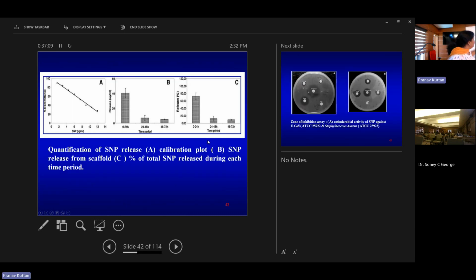So this is one method which we use for quantifying the silver nanoparticle. As it releases, HCl will be added. So silver will react with HCl, and AgCl turbidity will be formed. That turbidity will be evaluated as a percentage transmittance, so we can find out the concentration. And it was found that within 72 hours, almost all the amount of silver is getting released.